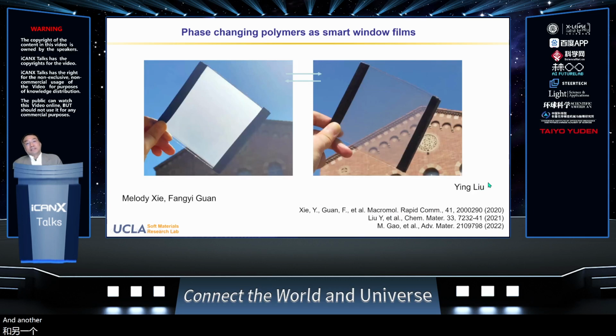And another interesting point: I already mentioned that the polymer in the semi-crystalline state is opaque. When it's heated, it's transparent. So we can use this, coupled with a dual heating electrode, to show this sort of smart window film. We can reversibly control its opacity with dual heating.